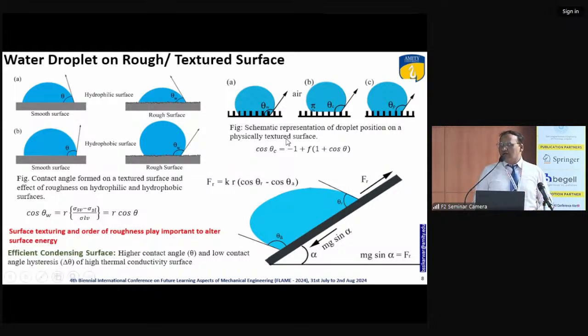These are the expressions available in books, where we can find the contact angle of a droplet sitting on a textured surface and on a rough surface. Here you can see a droplet on an inclined surface that is deformed: the leading side angle becomes the advancing angle and the trailing side angle becomes the receding angle, and the difference between them is called the contact angle hysteresis. The contact angle hysteresis plays a role in the retention force, which provides resistance against the motion when we incline the surface.